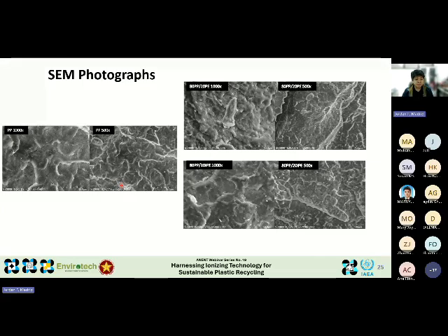This results in a noticeably rougher morphology of the blends compared to pure polypropylene. This roughness can be attributed to the presence of high-density polyethylene dispersed within the polypropylene matrix. As expected, the effect is more pronounced in the blend containing more high-density polyethylene content, which is the 80-20 polypropylene HDPE blend.